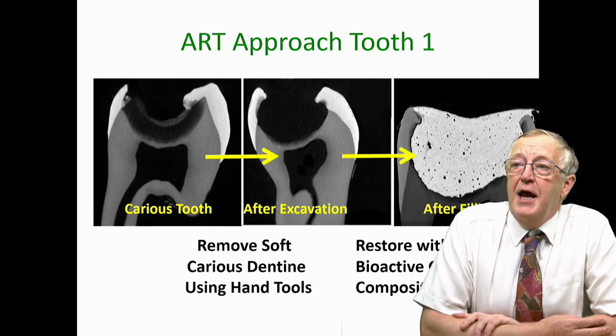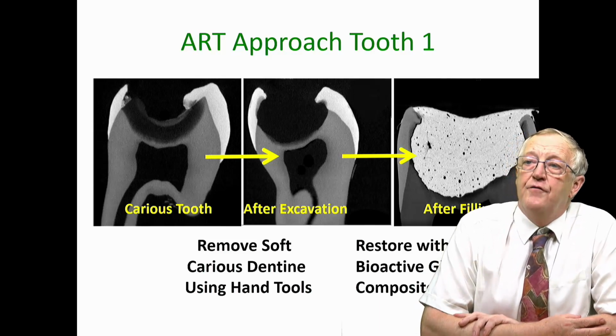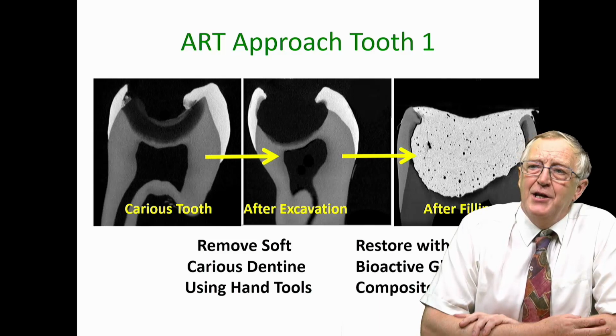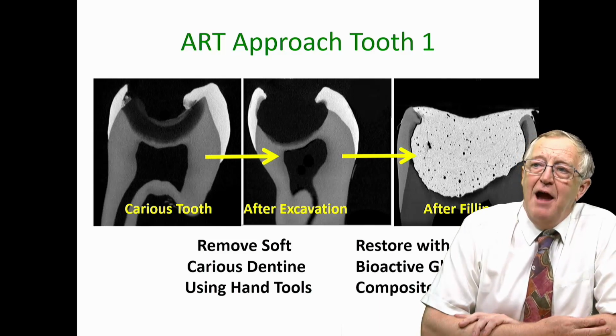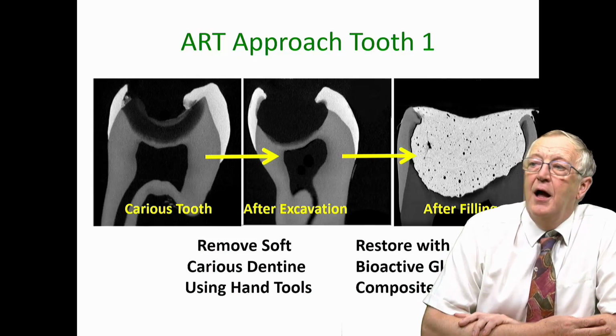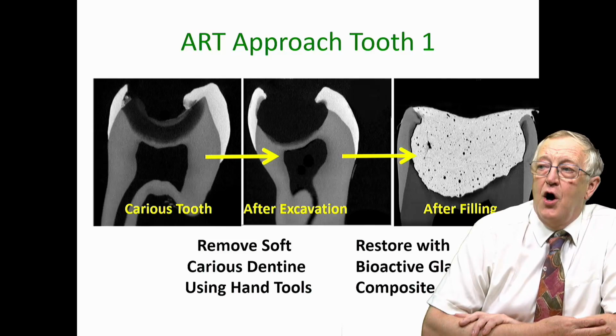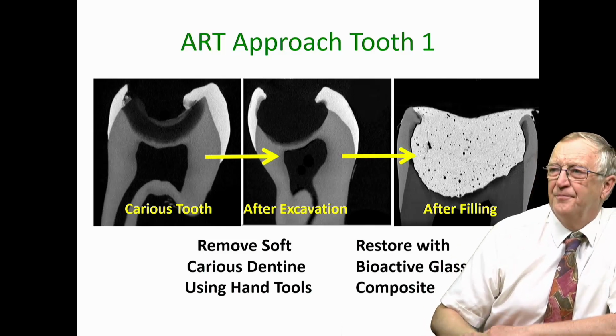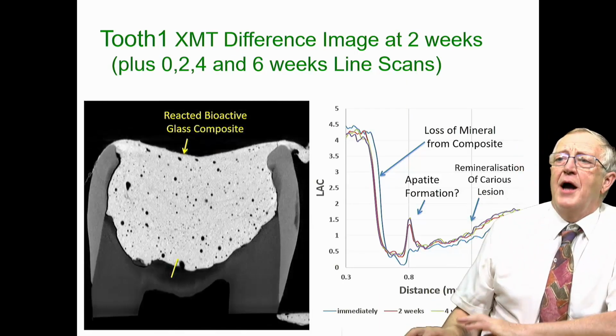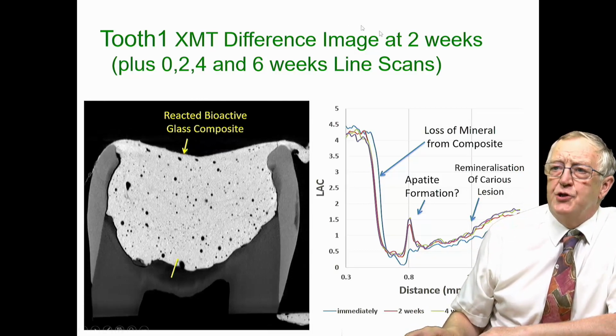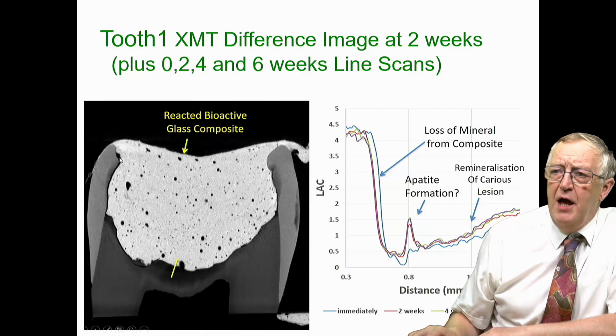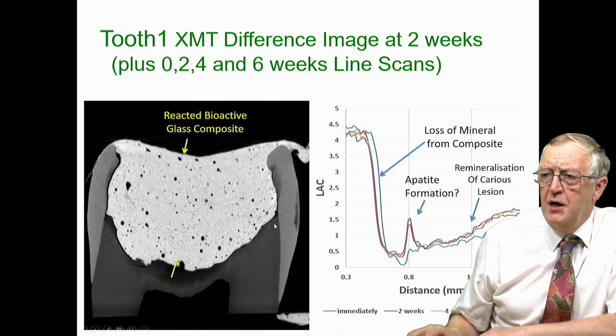So here we have an X-ray microtomography slice on the far left of the carious tooth. We then hand excavate the carious lesion, which you can see in the middle, and then we fill with the bioactive glass composite. So here we have the bioactive glass composite, and the image is at 2 weeks, but what you can see here, if you look carefully down here, can you see the marginal gap that's present? You can see, in fact, a white spot lesion here, and you can also see the carious lesion.